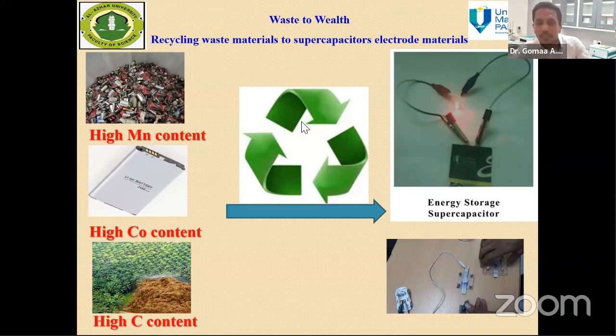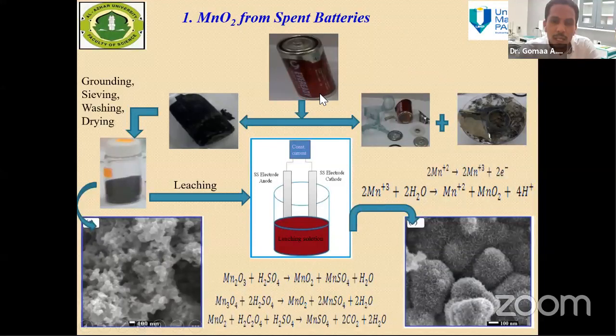So we start from spent carbon battery, for example, manganese oxide from spent battery. We start from zinc carbon batteries, our dry batteries, using an electrochemical technique, electrodeposition, after dismantling them into their component parts. We use the cathode powder, which is manganese oxide and carbon material. We leach this cathode powder to get a solution of manganese species. After we get the solution, we electrodeposit the manganese by applying electrical potential to produce manganese dioxide nanoflower sheets.